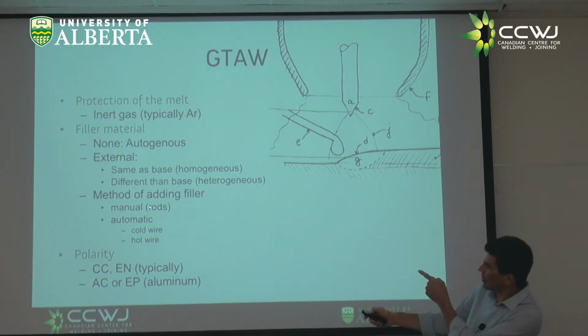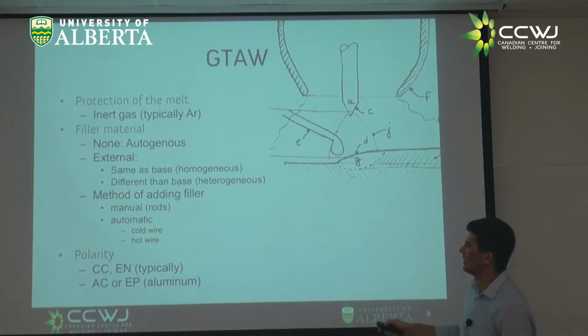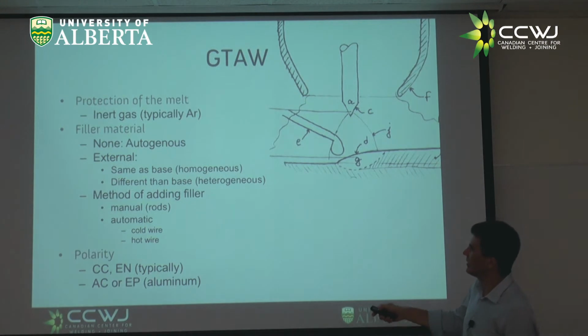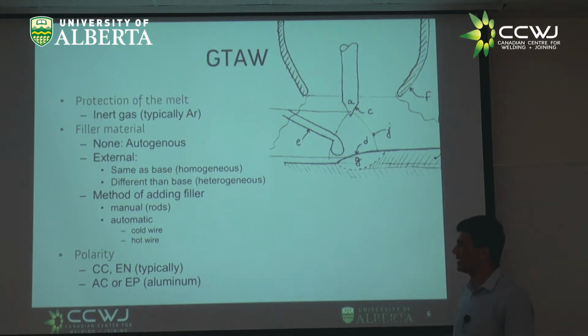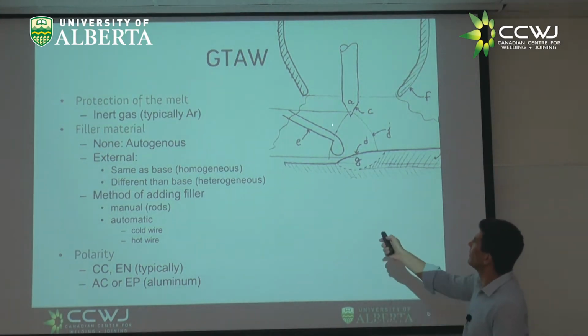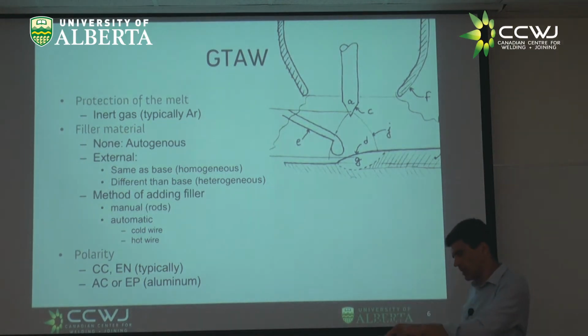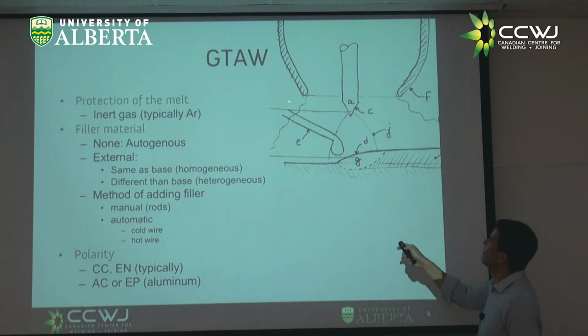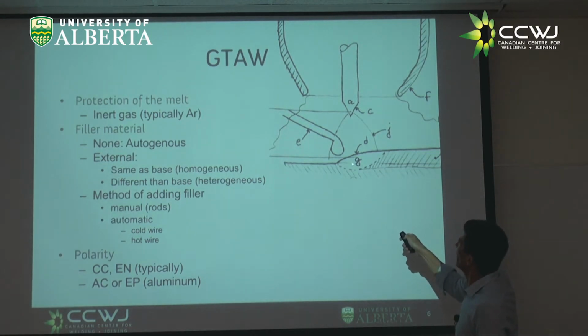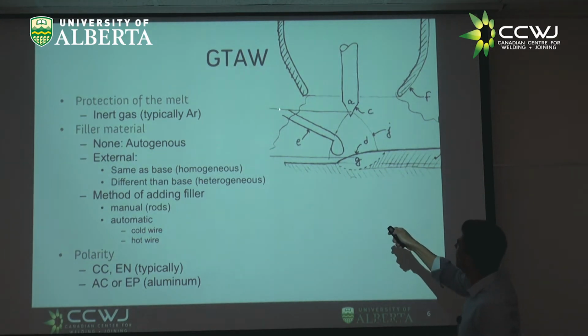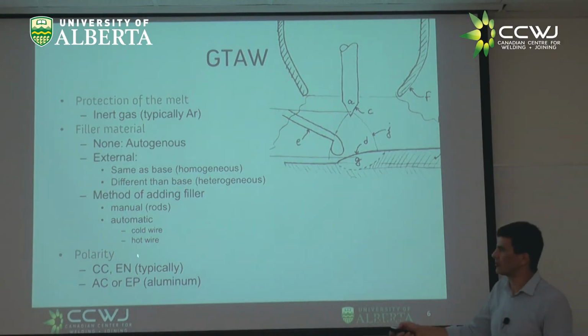The R stands for rod because you can use it for TIG. Or can be automatic. You can bring this from a machine, you push it. And if you just push the wire in, it's called a cold wire. But if you make this wire touch the weld pool, the molten metal there, the joule heating of another power source circulating current through this would heat up the wire, and it's called hot wire.